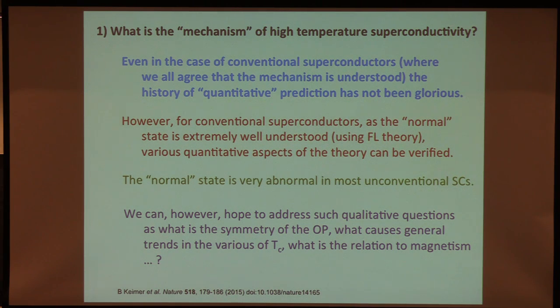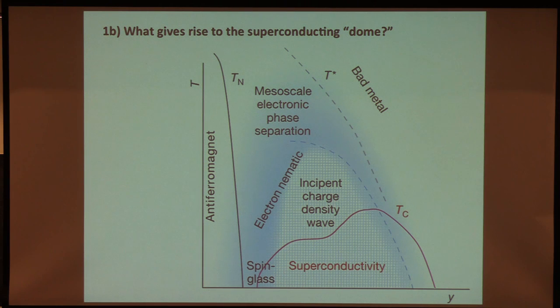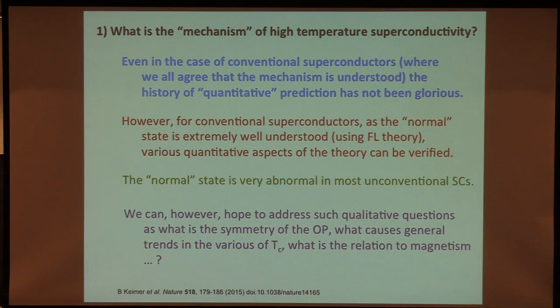Now, we still can hope to address some qualitative questions, like look at the band structure and predict what the symmetry of the superconducting order should be. For instance, that was done in the iron-based superconductors moderately successfully on theoretical grounds. It's always non-S wave, but it's not always D wave, is that right? Actually, in the iron-based superconductors it's even S wave, but it's always unconventional. That is to say, it changes sign from one piece of the Fermi surface to another. So it can do that in an S-wave way.